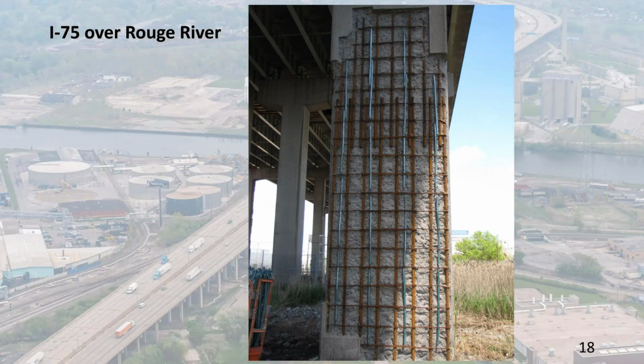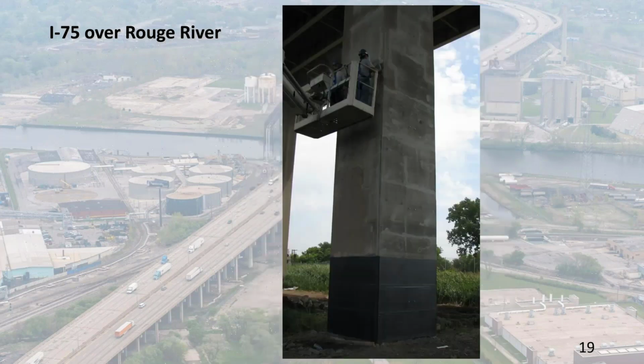So you remove the old unsound concrete, and then you begin to prepare the column for the FRP wrap. Are we on to the next stage? Okay, excellent. First off, of course, you apply the patch material, let it cure. You want to make sure the edges on square columns are rounded to reduce the stress on the FRP, and typically that's a 1-inch radius. Certain manufacturers may specify a preferred radius. Some may be smaller or larger, depends on the system, but they're roughly around the 1-inch ballpark.